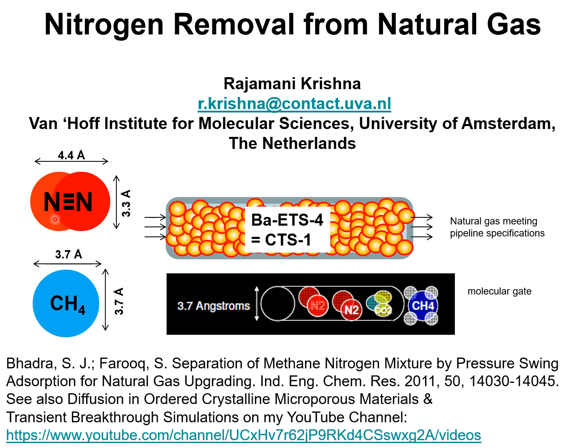For most known adsorbents, however, the adsorption selectivity for separation of nitrogen-methane mixtures is in favor of methane due to its higher polarizability. One practical solution is to rely on diffusion selectivities by using microporous materials such as LTA 4A zeolite